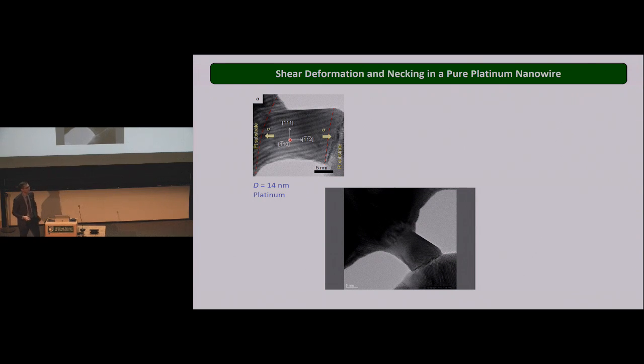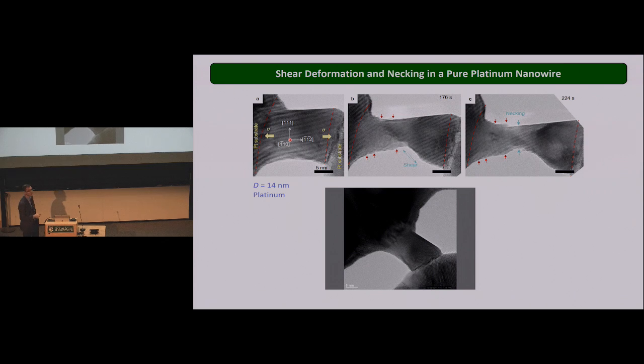So we have silver and platinum. Now, if you take bulk silver and platinum, they pretty much have the same type of ductility, right? They are largely ductile metals. Well, in this case, for platinum, when you use a platinum nanowire or nanocrystal, it's actually pretty brittle. It has shear localization and necking, and so the ductility is relatively limited to just 10-20%, which is low for this type of material. So you'll see that in the video here.